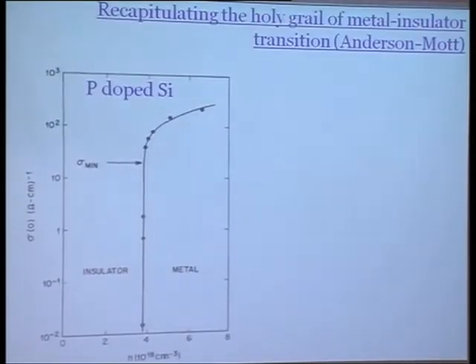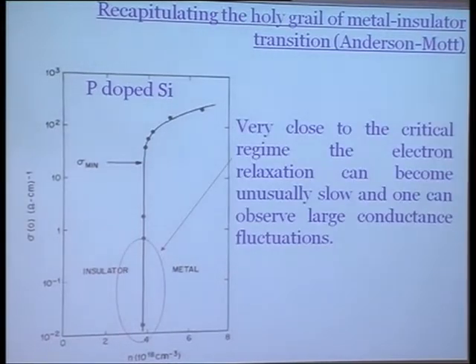Now let me come to the holy grail of the insulator-metal transition, which Professor Ravin Bhatt was referring to this morning. In my opinion, this still remains one of the unclean systems where a lot of work can be done. In the context of today's talk, the region that we'll be sitting in is this kind of region, but not in phosphorus-doped silicon, rather in the manganites, and it is very close to the critical regime.